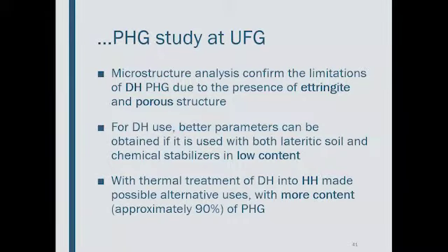Then with this study, we conclude that the DH type presents limitations because of the presence of ettringite in the porous structure. DH maybe can be used if we combine it with lateritic soil and stabilizer, but in low content. And the thermal treatment works. We got better results using the hemihydrate type of phosphogypsum. And with this material, you can think about using more of this byproduct, which is a good point.